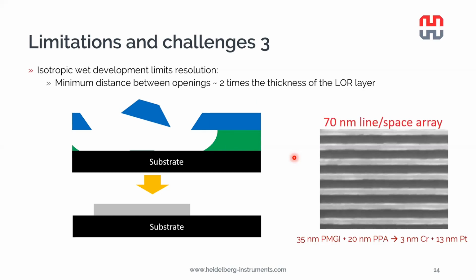We pushed this technique a little bit, and we managed to pattern a 70 nanometer resolution line space array by using 35 nanometers of PMGI and 20 nanometers of PPA and a 16 nanometer metal layer thickness. It might be possible to push it a little bit more, making the PMGI a little bit thinner still, but the metal then would not be very conductive anymore. And actually, we have another process for high resolution lift-off, which I will explain in a moment.